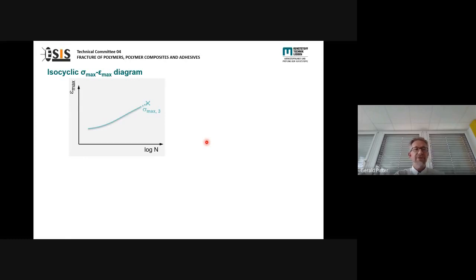now talk about so-called isocyclic stress strain diagrams. What do I mean by it? In this case, here in the isocyclic sigma max epsilon max diagram, we do a conventional fatigue test. We measure the strains. We measure the stresses. So the stress level is constant, for example, here in the test, and then we measure the strains as a function of the cycle number. And this, of course, is done, for example, in 4 different tests at 4 different maximum stress levels. And we measure the change of epsilon max as a function of the cycle number.